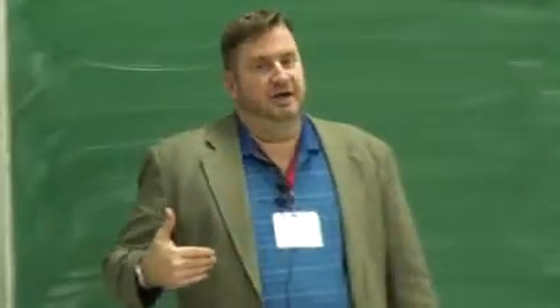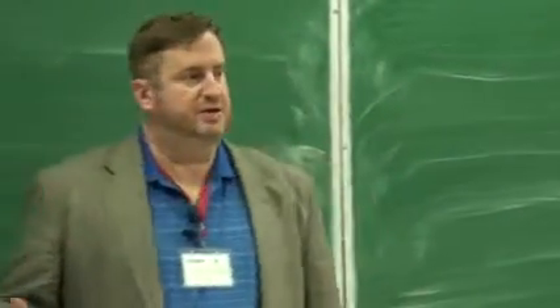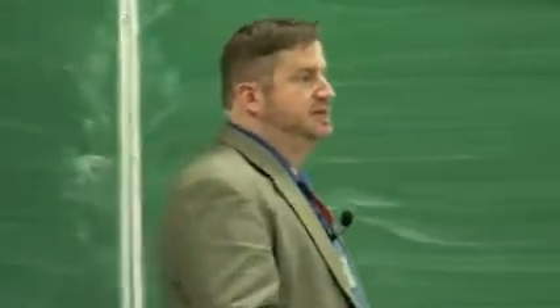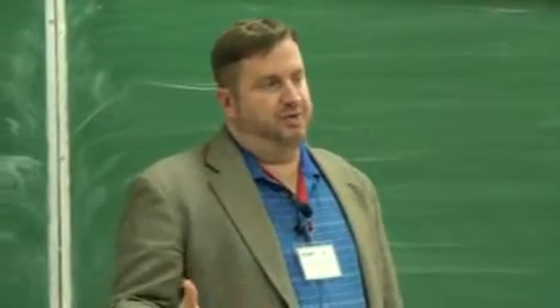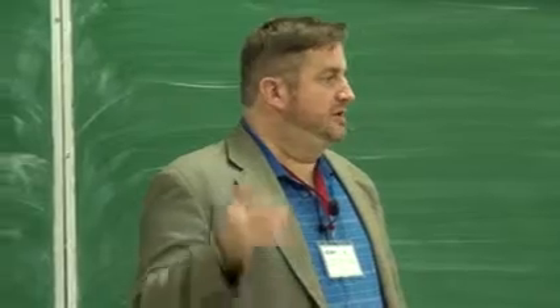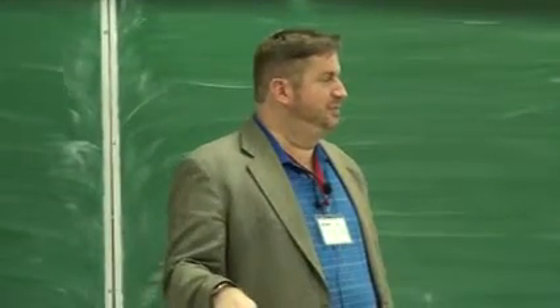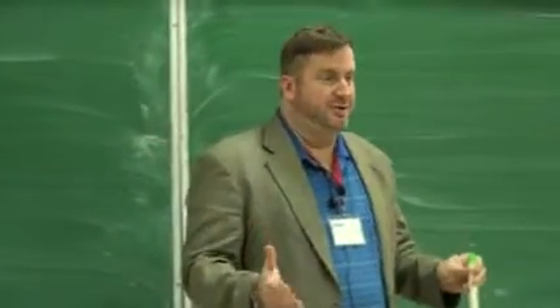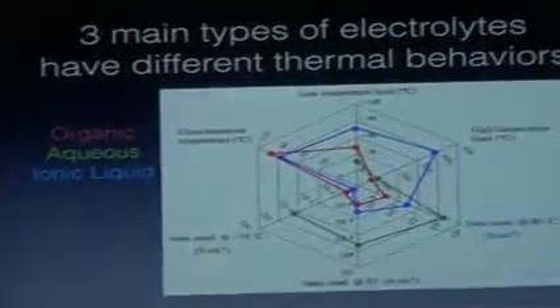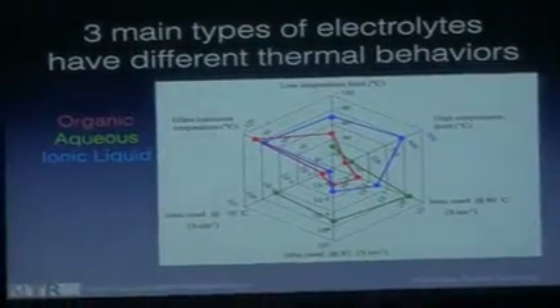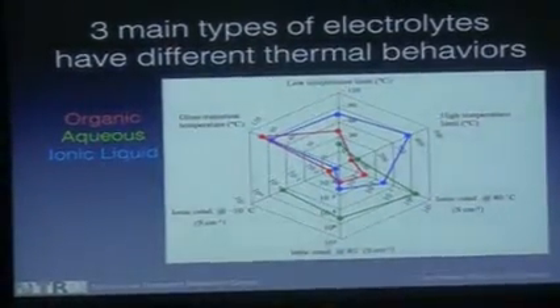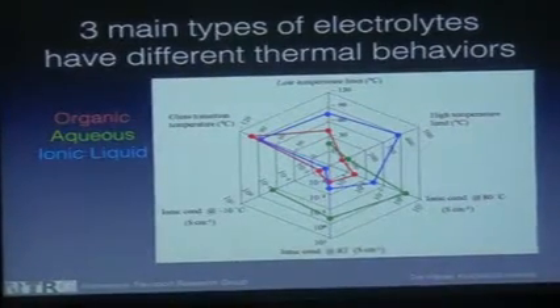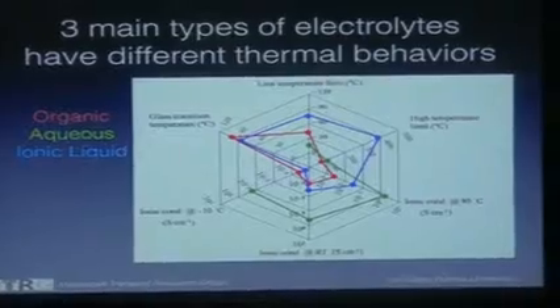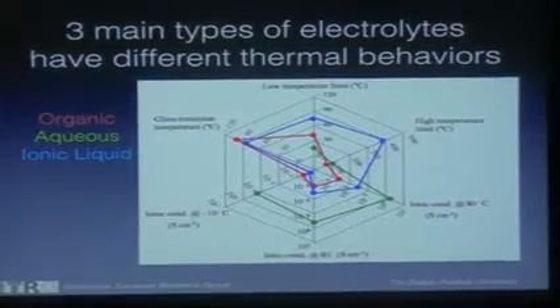So I think that a supercapacitor whose electrolyte freezes at minus 10 degrees C is not such a big problem here in Jodhpur, but it's a big problem in Chicago. Okay, and that's why companies want to make products that are generally applicable, and so that's a reason why that really hurts them in the marketplace. Kind of the compromise electrolyte between ionic liquids with their low conductivity but good temperature stability versus aqueous electrolytes with their very poor low temperature characteristics.